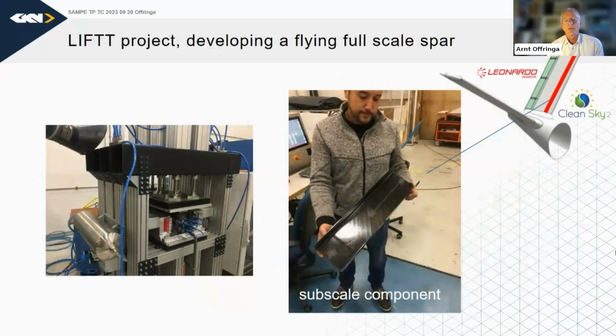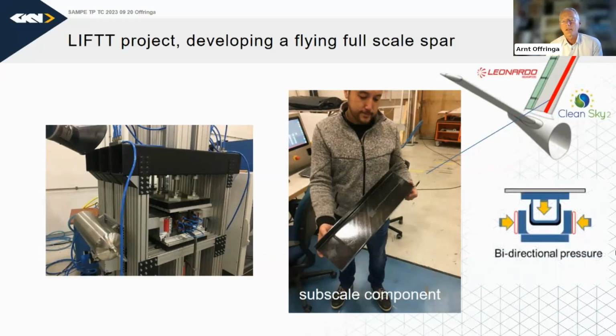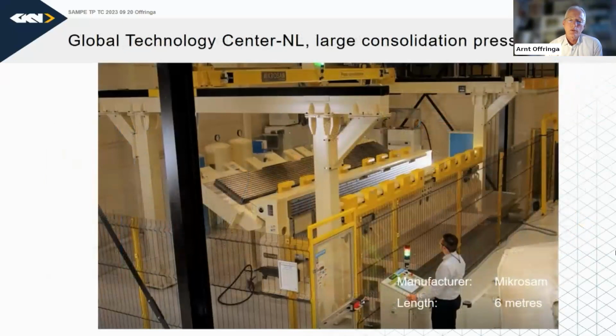And this picture shows the spar, but a subscale component which was developed in the beginning. The picture on the left shows a tool to basically compress the spar for the final part quality, a so-called co-consolidation tool. So we have several subsequent steps, each one with a short cycle time. And we use pressure in 2 directions to create the final quality of the part. And this slide shows a large press frame of 6 meters, which fits a tool. So the tool fits inside the frame, and the tool has its own pressure system, heating and cooling. So suited for large volume production.